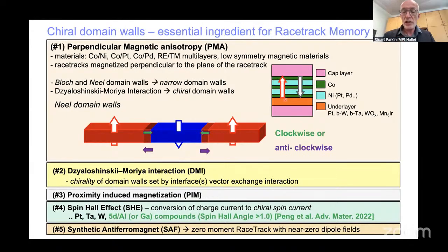So we've recently found some materials that have even greater charge to spin current conversion ratios. These are formed, for example, from iridium and aluminum, or iridium and gallium, which we think are very interesting compounds because at room temperature, these compounds, iridium aluminum, form atomically ordered species, enabling us to create very interesting heterostructures by epitaxy.